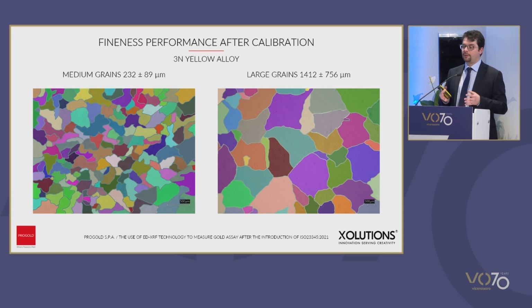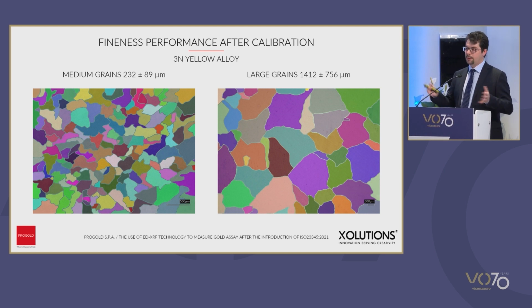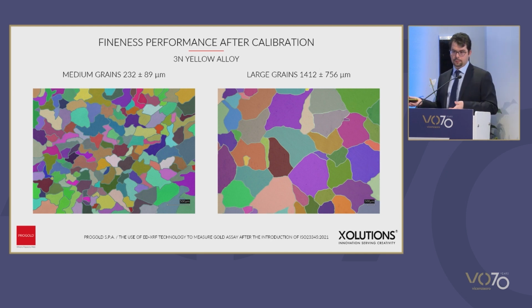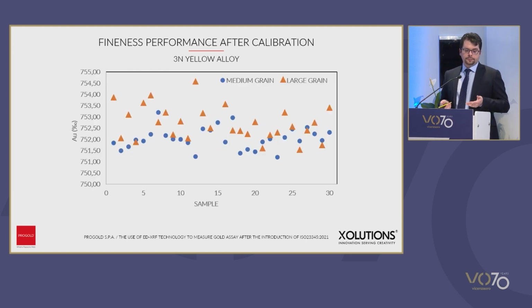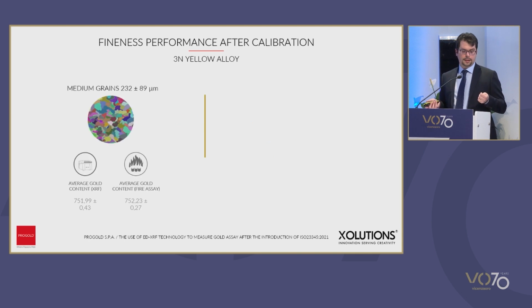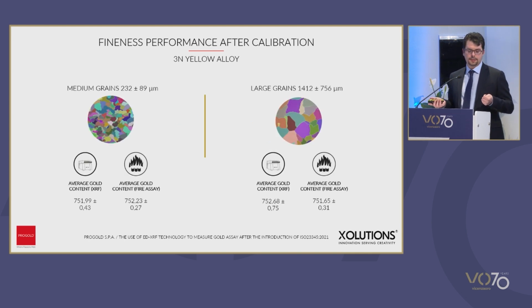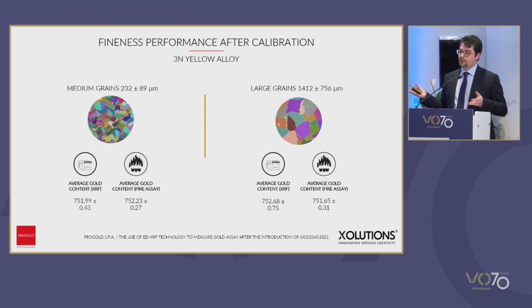Now, let's have a look at the results after making calibration, choosing these parameters on the three alloys that I mentioned earlier. Gold alloy, where we wanted to see whether there was a difference between the fine grain microstructure and the large grain microstructure. And these are the results that we achieved, and that are summarized in these two slides. And then we also did fire assay.